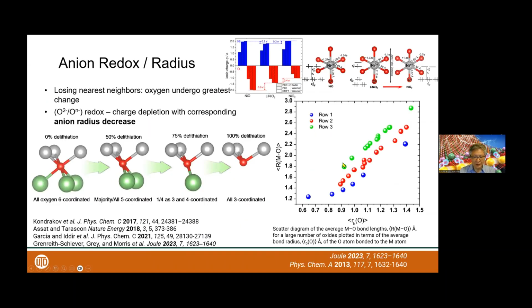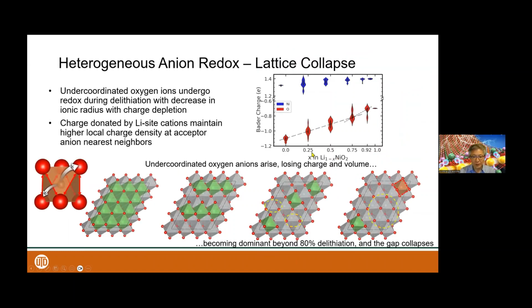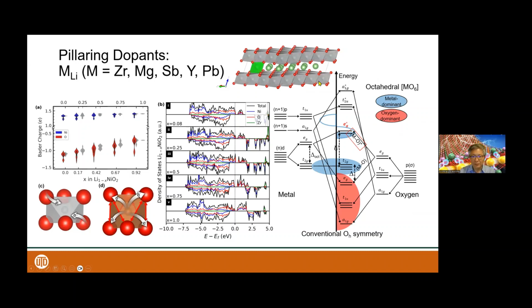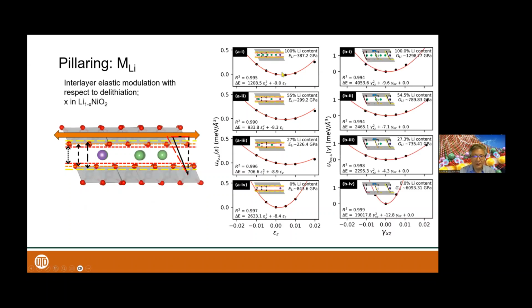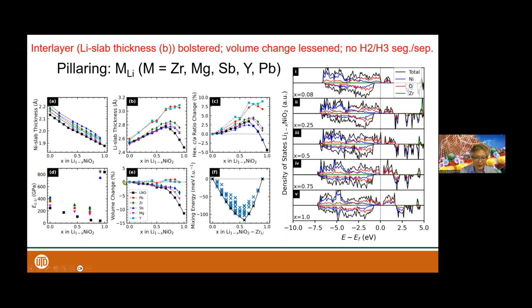Based on that, we developed a design strategy to suppress this volumetric change using a so-called pillaring element. When we introduced a pillaring element into the lithium layer space between the metal oxide layers, here's the summary of our finding: without a pillaring element, lithium nickel oxide volumetric change is happening rapidly over 70%. Depending on the choice of this element, we can practically achieve a zero-strain cathode material. So this is essentially solving the source of the problem. You can suppress the volumetric change; the shape change is still happening, but you can substantially reduce the mechanical strain driving the degradation of the cathode material.